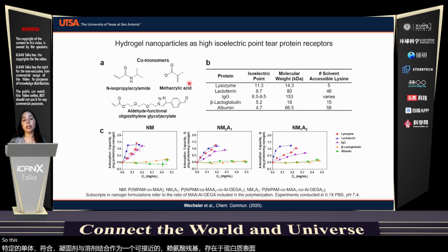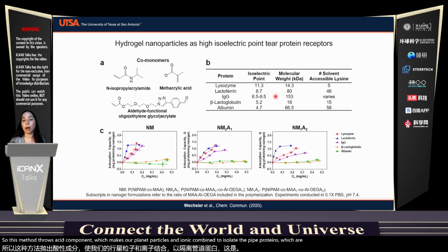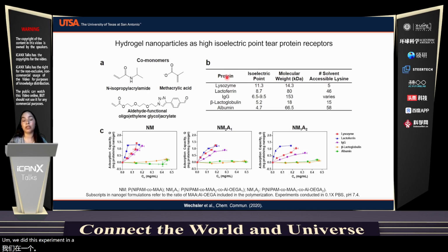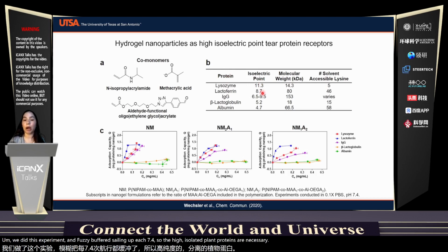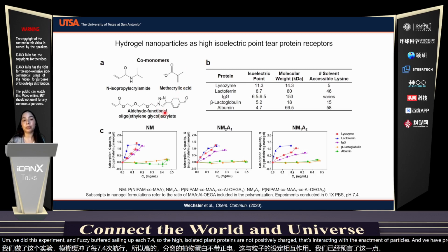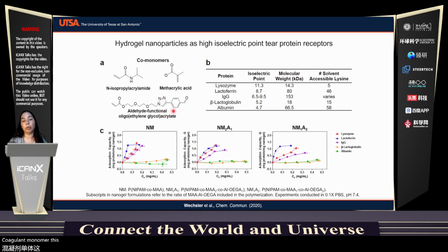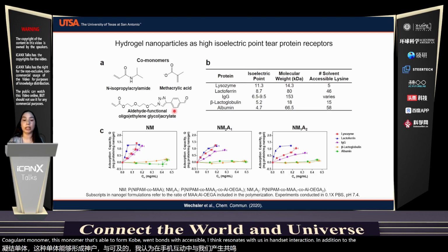This specific monomer can form covalent bonds with solvent accessible lysine residues that are present on the surface of proteins. So this methacrylic acid component, which makes our nanoparticles anionic, can bind to high isoelectric point proteins, which are net positively charged. We did this experiment in phosphate buffered saline at pH 7.4. So the high isoelectric point proteins are net positively charged, thus interacting with the anionic nanoparticles. And we hypothesized that incorporating this monomer that's able to form covalent bonds with solvent accessible lysine residues would thus enhance that interaction in addition to the electrostatic interactions.